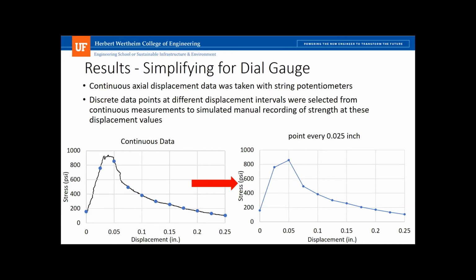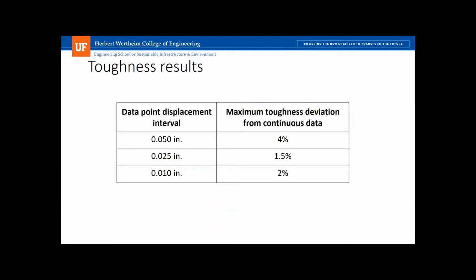The peak strength you can get because the machines typically have a method of giving you the peak results independent of you keeping track of it during the test. So that's not a problem. But the area, we were concerned that would matter if you simplified it further. We found that as long as you're taking results about every 0.025 inches, it only made a difference, a deviation of 1.5% from taking continuous measurements. Very little difference, and gives us confidence that you can take these results manually, writing these results down.